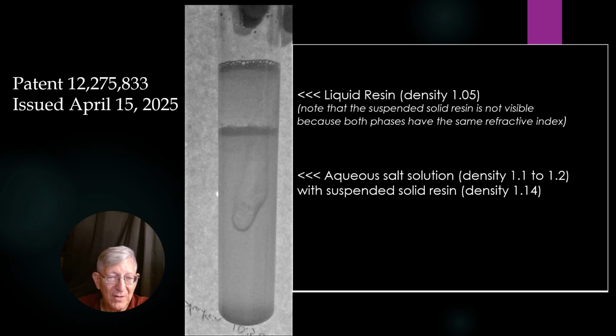Now down below, what we have is a dense solution of literally sodium chloride in water. That water, and especially the sodium chloride solution, is immiscible with the liquid resin. And so you get the two phases, and the aqueous solution is primed to have a density between, it's actually a gradient at the bottom where you have actually some solid sodium chloride. You have a density of about 1.2, and then up towards the top it's about 1.1. And lo and behold, the suspended solids have a density of about 1.14, and so they sink out of the liquid resin and end up in the aqueous density gradient.